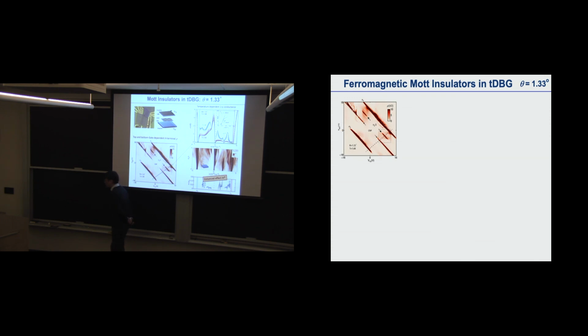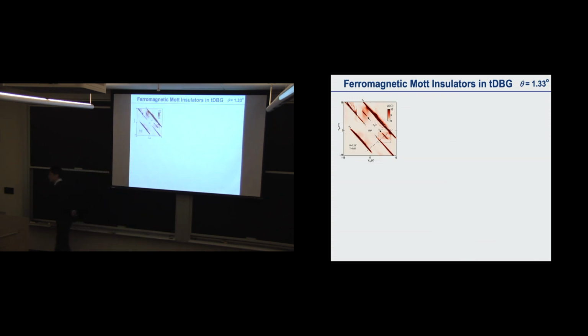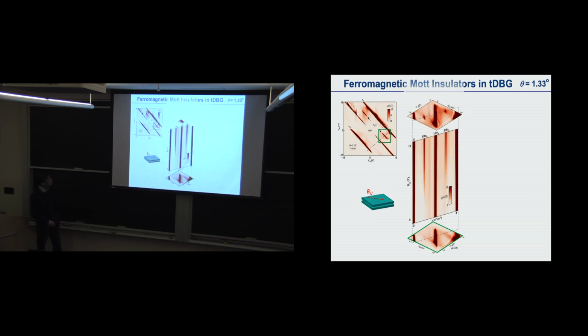What is interesting is applying a magnetic field to the system. We choose one of these correlated states and apply a magnetic field to see what happens, especially applying an in-plane magnetic field, which in principle doesn't touch the orbital structure, so we can just look at the spins. This way you can tell whether the spin is aligned or anti-aligned.